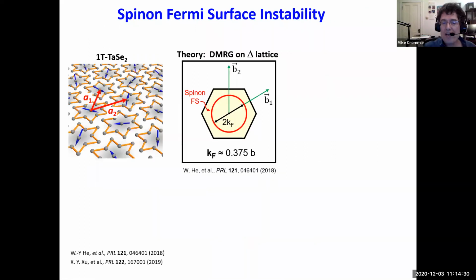So that's the idea. So then we have to ask ourselves, what should it look like? What should the Fermi surface look like for a spinon Fermi surface in a triangular lattice? Well, it turns out that this question has been addressed by theorists. There are predictions out there, made by Patrick Lee's group a couple of years ago. They did some calculations using density matrix renormalization group theory on a triangular lattice, and their goal was to model the behavior of 1T-TaS2. But the material parameters of 1T-TaSe2 are pretty similar, and so those theoretical results should also apply to 1T-TaSe2.